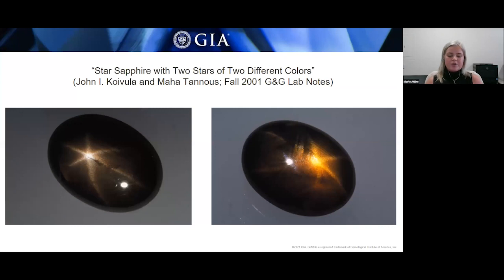The silver star was created by inclusions that were right at the surface, which greatly reduced the body color of the sapphire's influence on the color of the star. While the inclusions responsible for that golden star were farther from the surface and reflected through that yellow-brown body color, giving it that nice golden asterism.